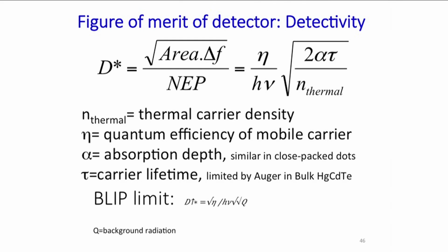Now, if we want to go further with this, we have to go after that figure of merit, which is called the detectivity. Detectivity is one over the minimum detectable signal, which is basically the noise of the system. This is the formula for it. One can relate this to some basic properties of the material, such as the lifetime of the excitation, the absorption, the inverse absorption length of the material, the quantum efficiency of charge separation, the wavelength at which one operates, and the number of thermal excitations. That's one way of calculating this. And we can calculate this for the nanoparticles. And in principle, we should do much better than the bulk as far as tau is concerned. We should do the same for alpha, the same for eta, and the same for n. So in principle, we have a fundamental advantage over the bulk material.